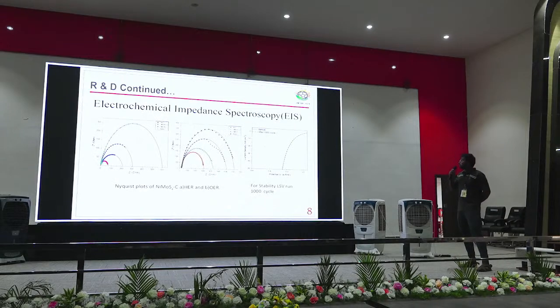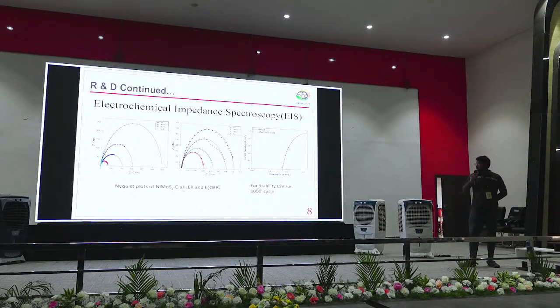The electrochemical impedance spectra, Nyquist plot, was fitted with a Randles circuit. The smaller semicircle represents faster kinetics, the larger semicircle represents slower kinetics. This is a stability curve run for 1000 cycles. There is not much difference between before and after.